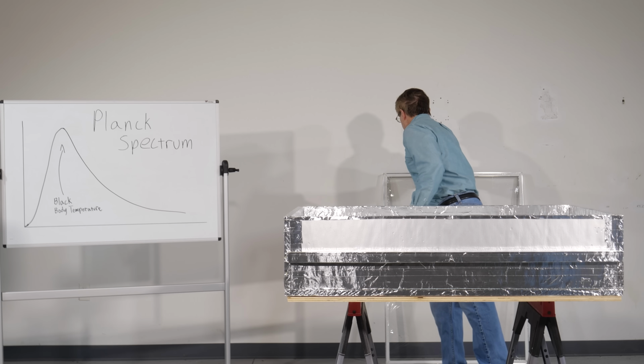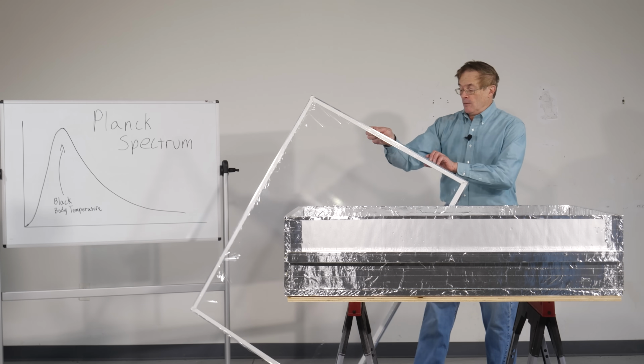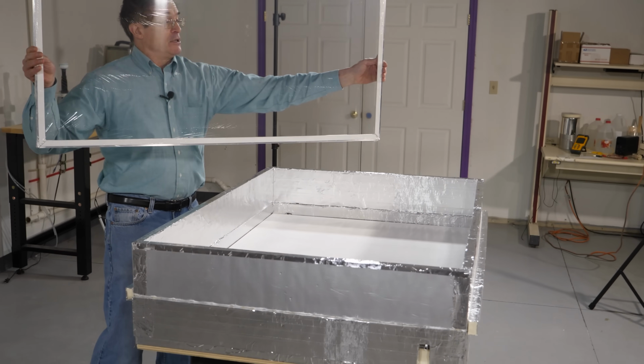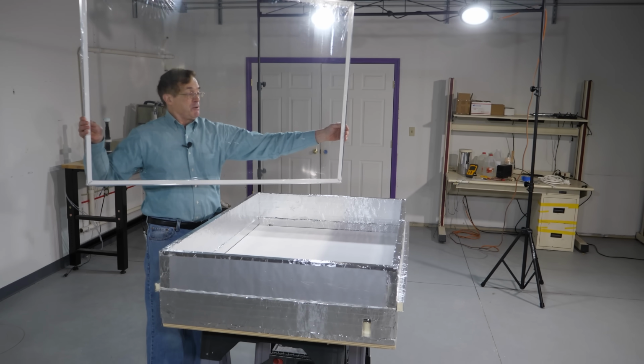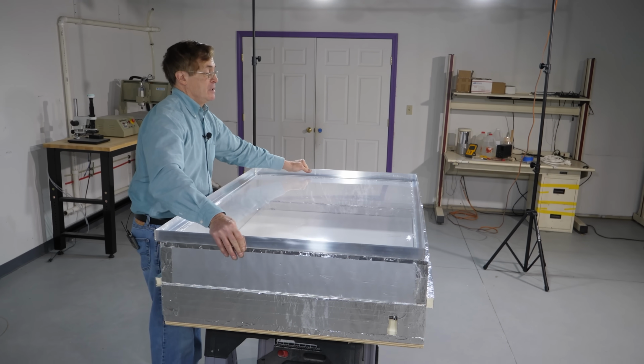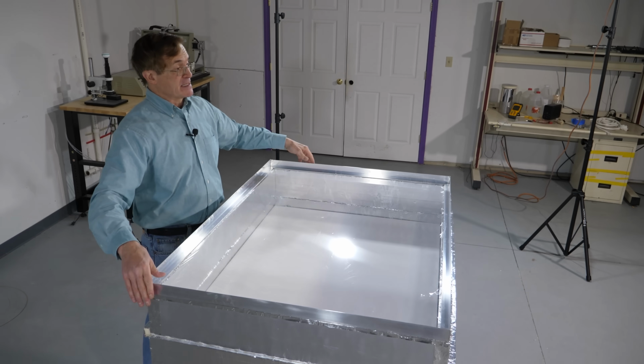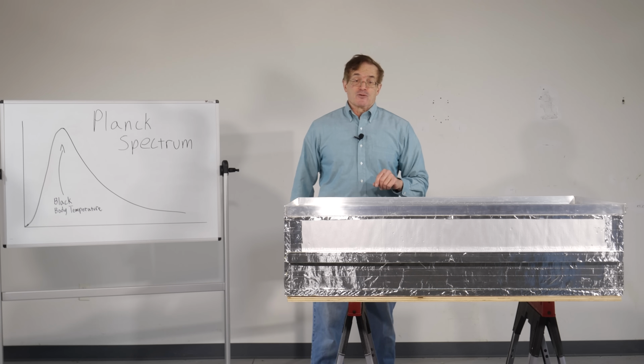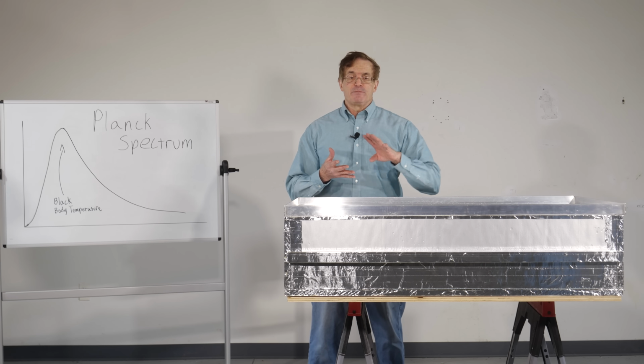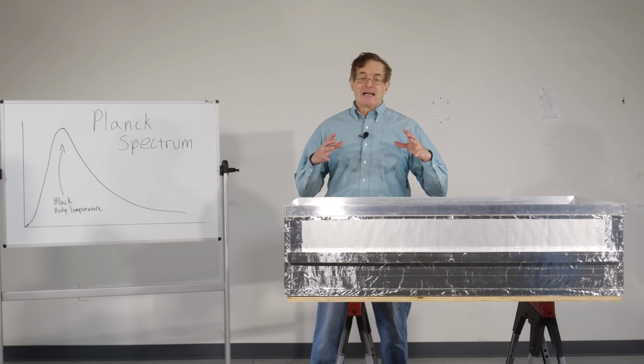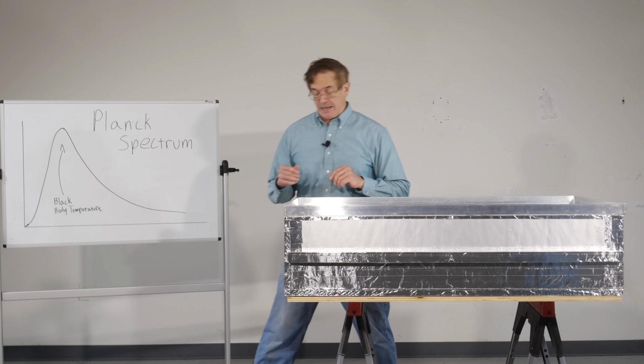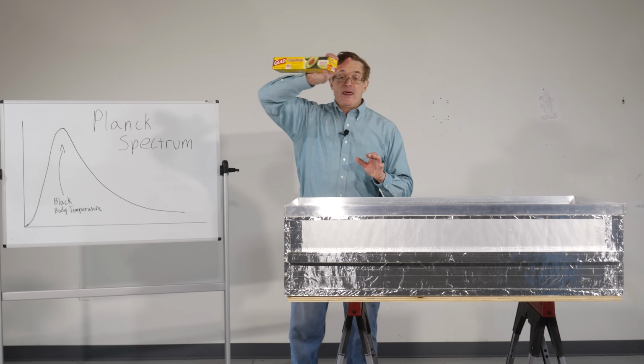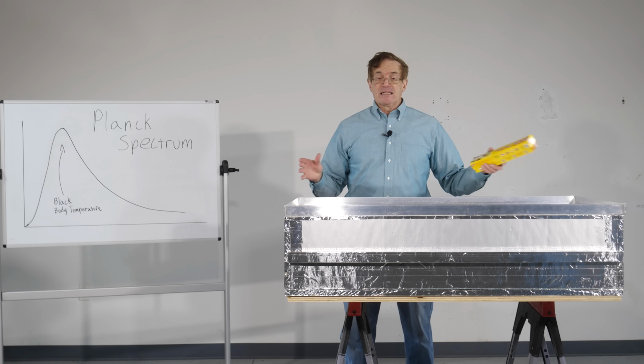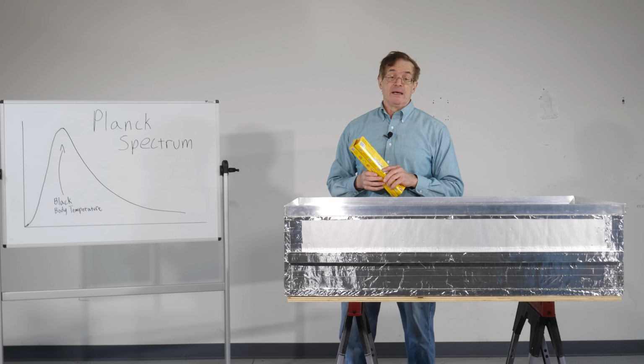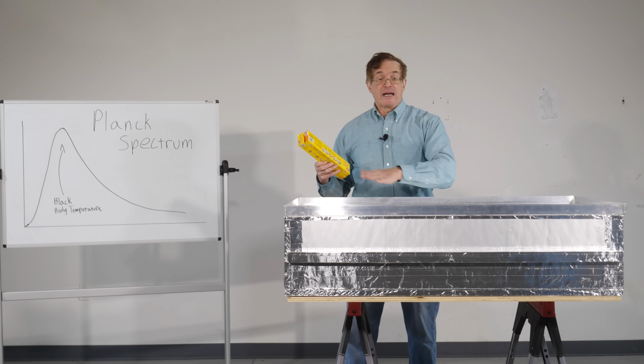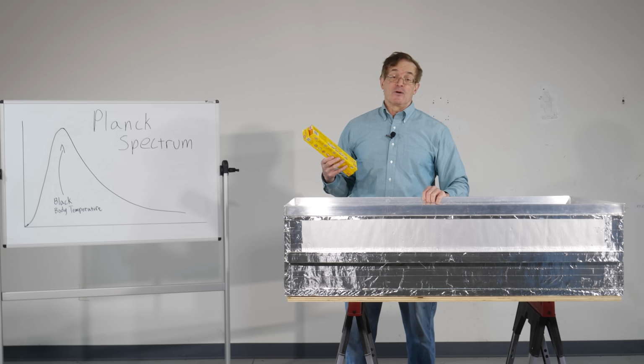So then the final step was to build a window. This window consists of an aluminum frame on which we stretched a plastic film to act as a barrier to airflow and allow the air to stagnate inside of the structure. The plastic is kind of interesting. If you use glass, plexiglass, polycarbonate, it will absorb the infrared. It's not transparent to allow the infrared to go up into the sky. Turns out, this stuff, plastic wrap, polyethylene is extremely transparent to the infrared, and so it can radiate out right through this but prevent airflow going across it. And it's lightweight and it's very convenient.